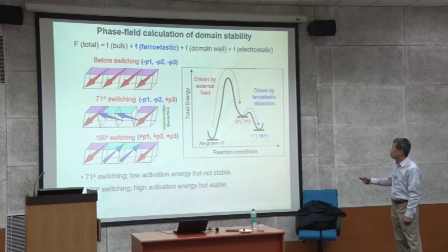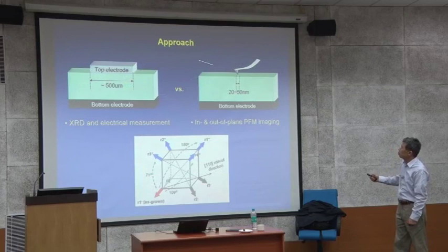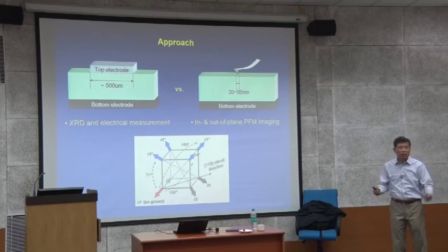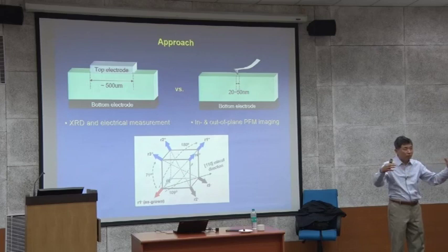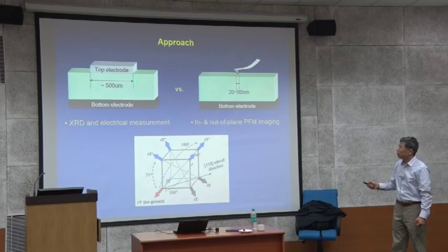So initially, in order to really understand this, you make a large electrode and a smaller electrode, and you compare them, because of the interfacial area divided by the volume. For a smaller device, you have a lot more interfacial energy than volume energy, right? So that means the energy due to some kind of elastic constraint is not likely severe in a large device, but when it's smaller and smaller, you have a much more serious problem.